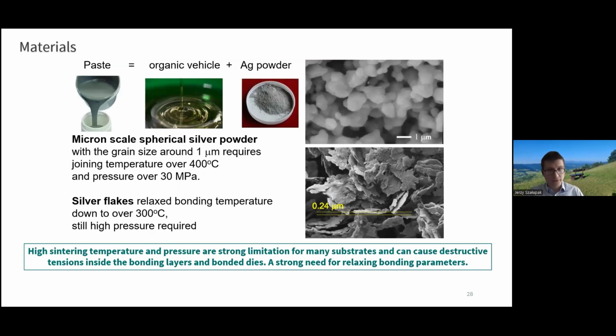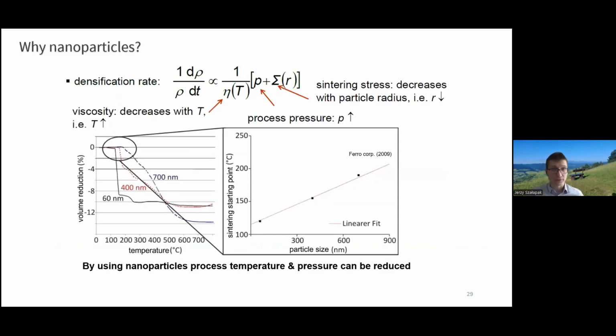The melting point of silver is 961 degrees. Sintering silver in the presence of glass frit reduces the temperature to 600 degrees, but it's still way too much for many electronic systems. At the same time, the glass frit deteriorates the thermal conductivity and electrical resistivity of the layer. Using the low temperature joining technique with silver microparticles, it is possible to obtain a single layer at the temperature of 400 degrees. And with silver microplatelets, you can reduce this temperature even to 300 degrees, although the pressure used is the limitation. It ranges from 20 to even 80 megapascals, which may damage the attached electronics component.